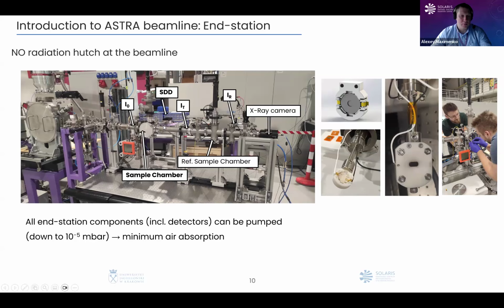What is also important, as you can see here, is that all of the elements are closed, and we can keep the pressure in our end station in a low vacuum, around 10 millibar, up to atmospheric pressure. It allows us to run experiments in transmission mode, which is dedicated to materials with a higher concentration of the absorber, or in fluorescence mode where you have a low concentration, less than 5% of absorber in your materials. When we use fluorescence mode, we can make such experiments in a low vacuum or at atmospheric pressure, and it also allows us to go to these low energies.